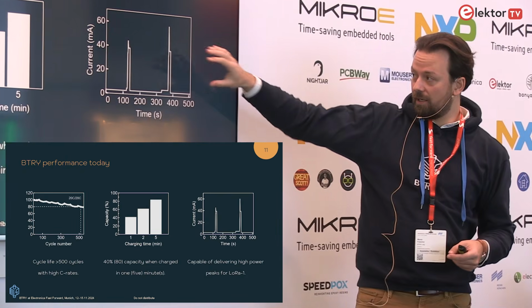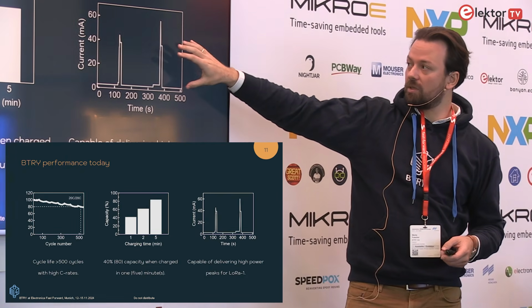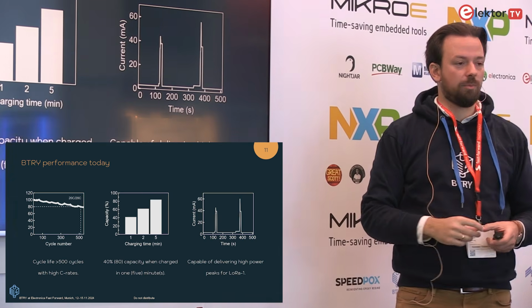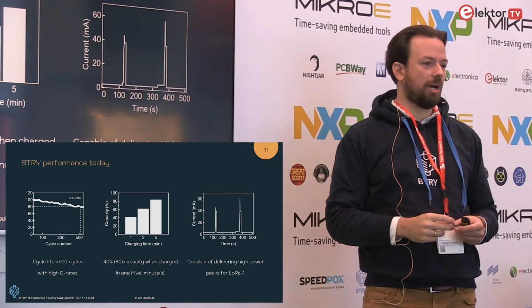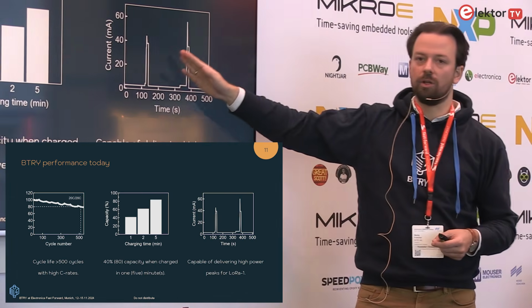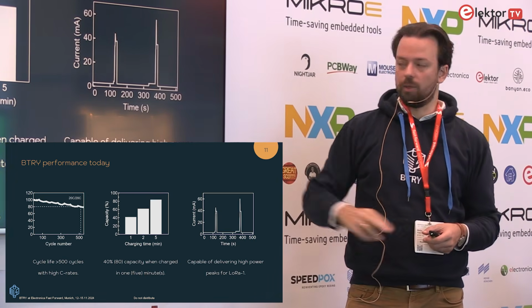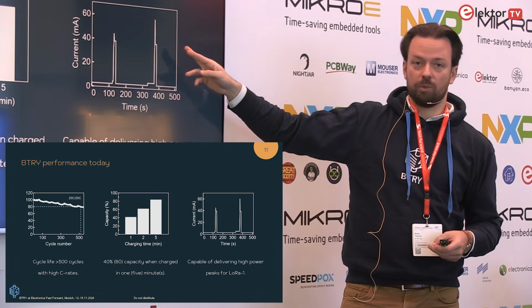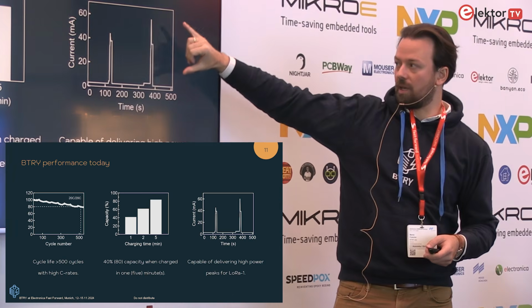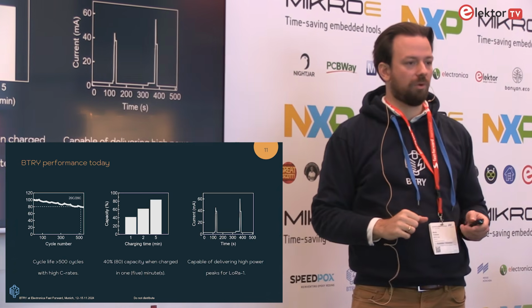And here you see the current performance, so we can achieve this 60 milliamp. This was, in this case, from a customer who asked for this, their protocol for sending LoRa signals. We can do this with a cell which has little capacity, but already has very high C rates to have the power for peak performances.